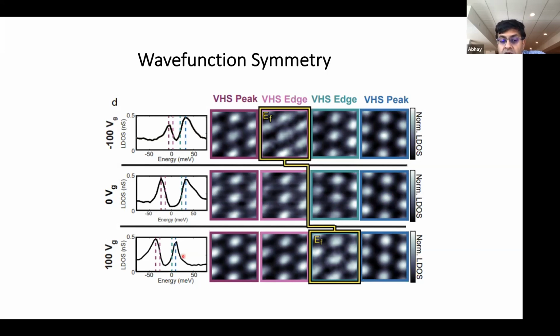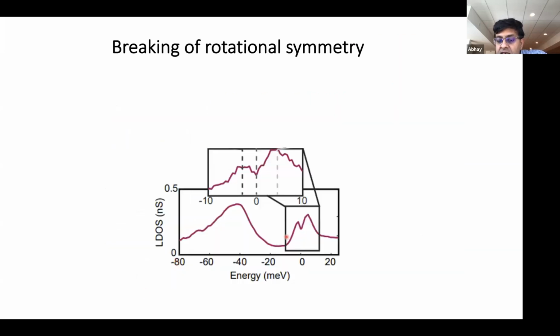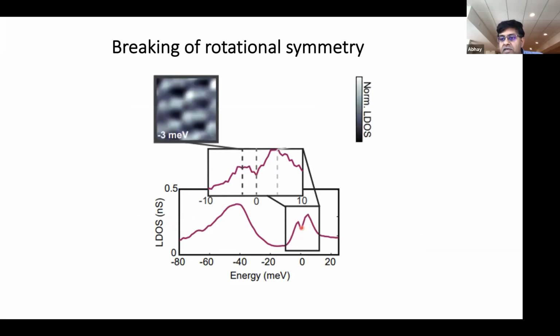And what we could do is change the doping by applying this gate voltage, and we brought it to this condition where you have precisely 1/2 filling of one of these Moiré subbands. This is that doping condition, where we brought the chemical potential to exactly 1/2 filling, and you can see a little gap start to develop at the Fermi level. At this particular condition, if you image the local density of states, we found, much to our surprise, that the threefold rotational symmetry is completely broken, right?